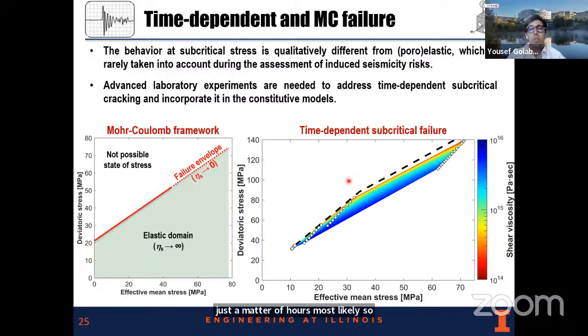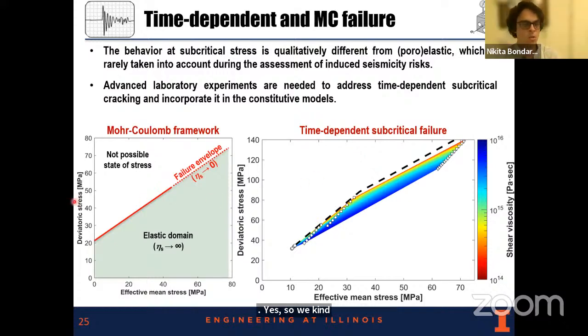And how did you choose the load? Is it some percentage of UCS? Yes, so we more or less know the failure envelope of this material. Of course, there are some uncertainties there, but we know what to expect in terms of the instantaneous strength when we just load until failure. After that, we usually start at somewhere around 50 to 55% of the maximum expected, and by small steps we bring it closer and closer to failure.